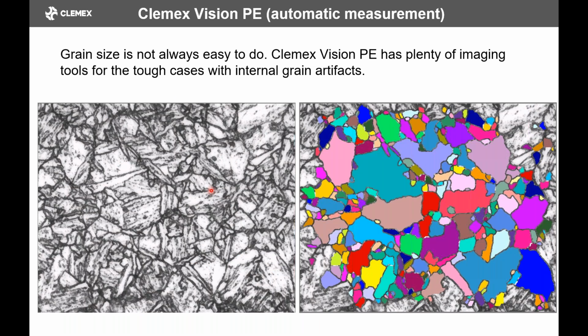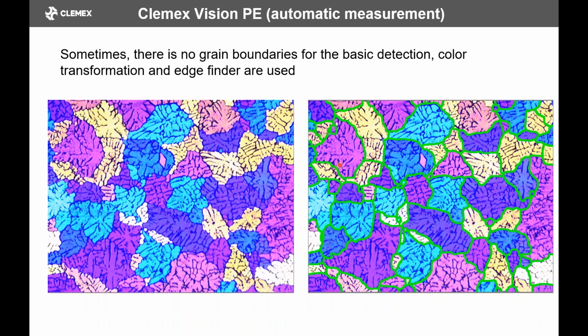Not all grain sizes are easy to do. This is an example of a material with a lot of noise inside, and it's very easy for systems without many instructions to pick this up as false boundaries. As you can see, we're getting quite good results. Another challenge is with these color grains. This is aluminum, so we don't have an actual boundary. There's a color transition, but not an actual boundary. So we add some edge finders and color detection to be able to pick that up.